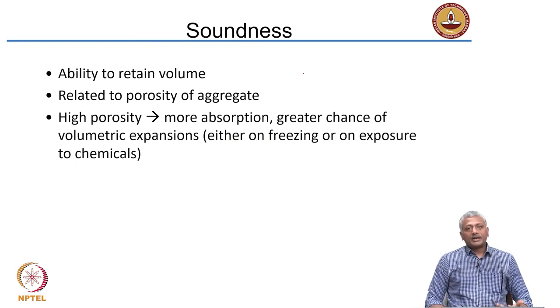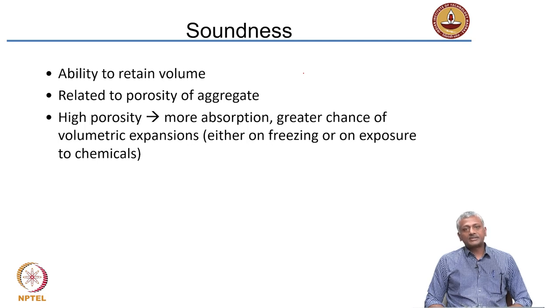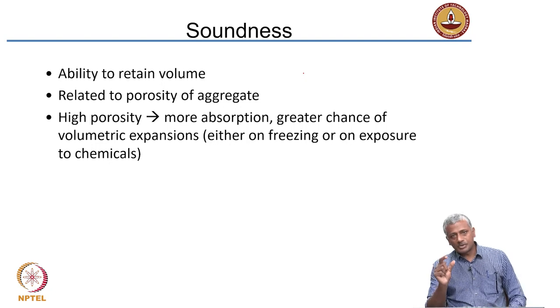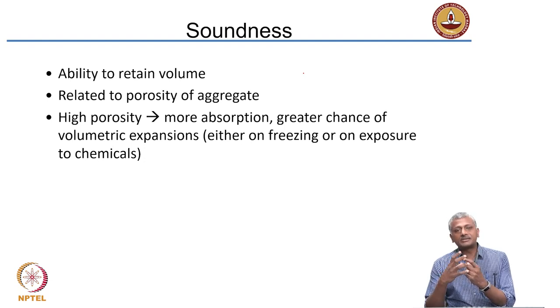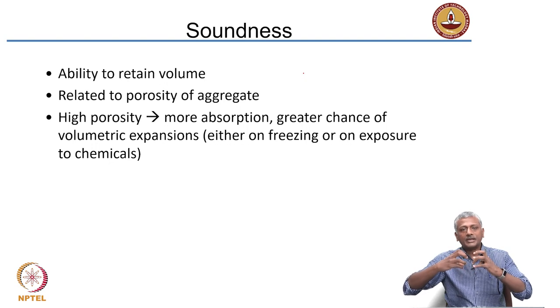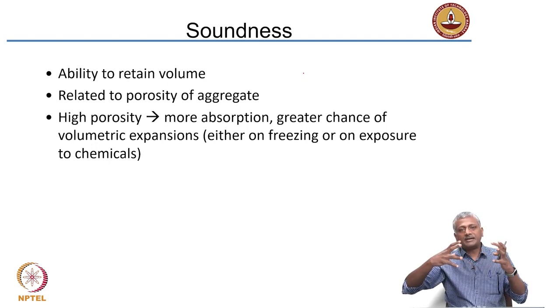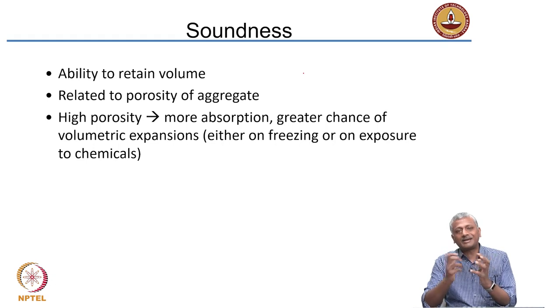Another important property of aggregate is its soundness. Soundness is the ability of the aggregate to retain its volume. Aggregates are porous, so they start taking in water and sometimes chemicals, and these chemicals may leave behind crystals inside the pores which could cause the aggregate to expand and crack.